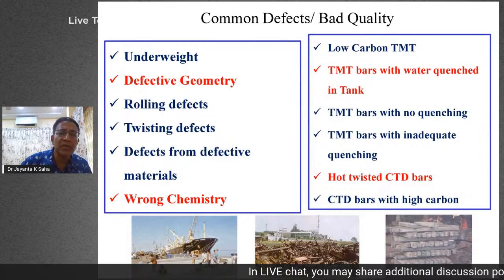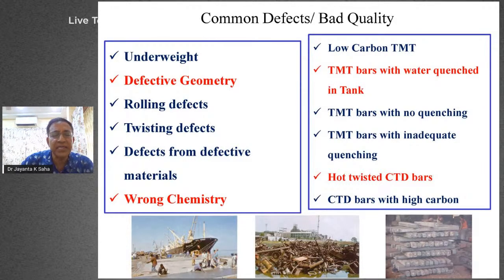So these are some of the TMT bars I have listed. These are the outcomes of this analysis: the bar weight per running meter, because when you are designing a structure, you are taking the weight of the reinforcement bar, there the unit length weight is under. The defective geometry means the bond strength comes through the geometry of the ribs. If the ribs are defective, if the height is less, then you don't get proper bonding with the concrete. Then rolling defects, twisting defects, wrong chemistry, then, as already mentioned, quenched in the tank, and very low carbon.